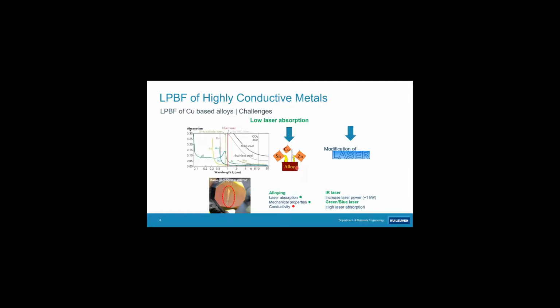We could also modify the laser source. There are, for example, these days, more and more powerful green and blue lasers. And you see that at these wavelengths, a green laser is located somewhere over here, copper already absorbs much more of the laser light, and it will be even stronger with the blue laser. And by the way, you notice similar problems for gold and silver. And as I will explain later, it's all related to the electron configuration of the material.